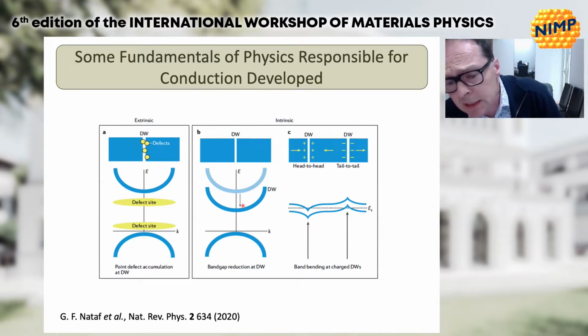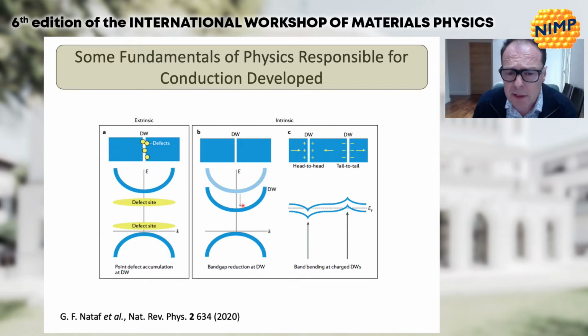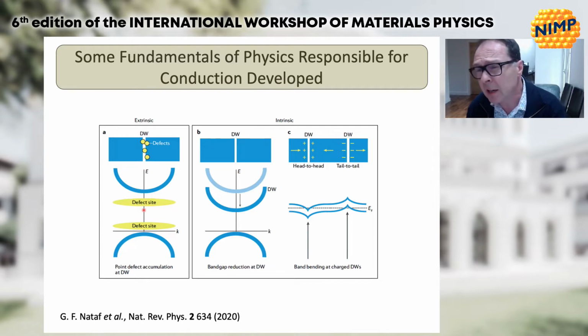In fact, several ideas. And there is indeed evidence in the literature for all 3 of these kinds of notions for what makes a conductive wall conduct. The first one is that basically they're not really conducting, it's just that they're kind of hoovers for the aggregation of defects, charge defects, that can act as defect donor or dopant sites within the band gap of the normal material. And I think Igor Stolichnow's seen some really nice evidence that in bismuth ferrite, this collection of defects certainly occurs.